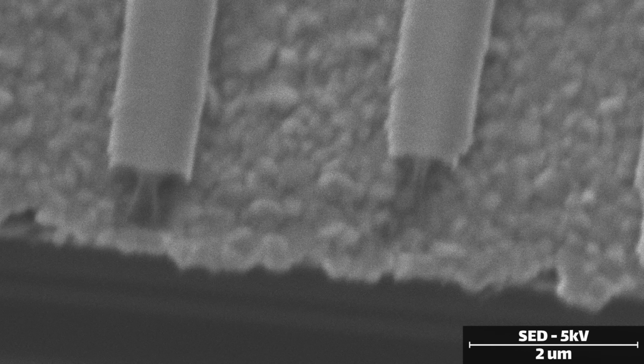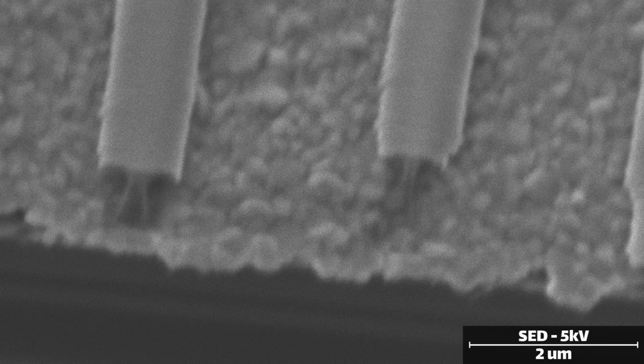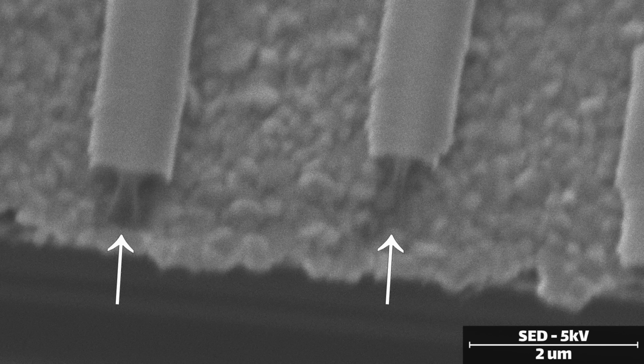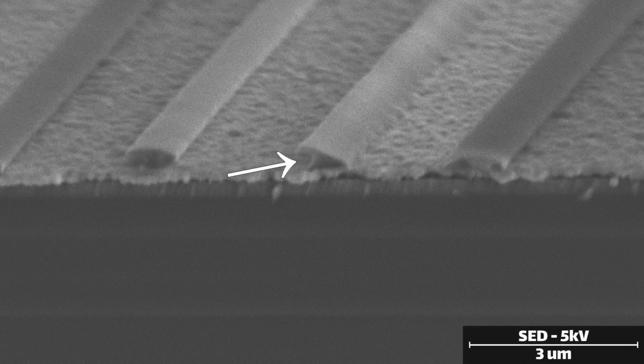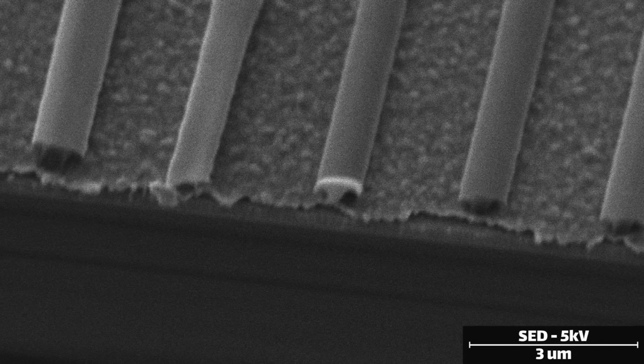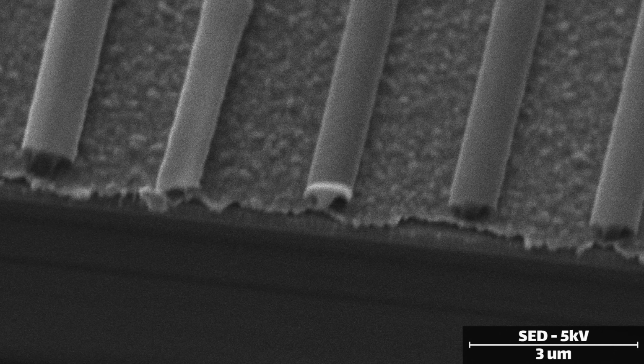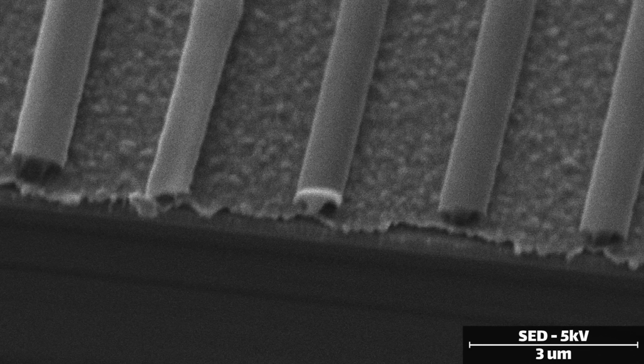It's a little hard to make out, but here's a cross-section view of some tests I ran. You can see like a T or mushroom shape. The broader layer at the top is the PMMA, and the narrower neck region is the MMA. You can also see that in this particular section, the aspect ratio of the MMA layer was too high, and it actually fell over during development. This would impact the resolution of the feature you're trying to make, or maybe even lead to a failure, not allowing the metal to lift off.